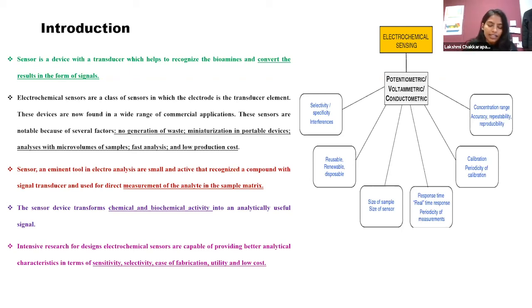Electrochemical sensing has a great impact, and it's also analyzed by different kinds of methods: potentiometric, voltammetric, conductometric. From the result, we could analyze whether the electrode has selectivity, specificity, interference, and is also reusable, renewable, disposable, and the size of the sample, and also the size of the sensor, response time, real-time response, periodicity of the measurement, calibration, periodicity of calibration, concentration range, accuracy, repeatability, and reproducibility. This sensor also helps us to convert chemical and biochemical activity into analytically useful signals.